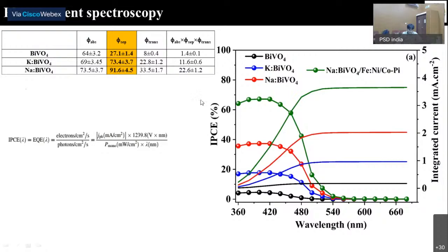And further, using our efficiency equations, we have calculated IPCE, that is incident photon to current efficiency. That means whatever light photons are falling on the electrode surface, how much percentage of that is being converted for the water splitting. So with the sodium doping, we can reach up to around 40%. So around 40% of the light which is falling on the surface, we can use for the water splitting purpose. So that means doping is having a positive effect, especially with the sodium doping.